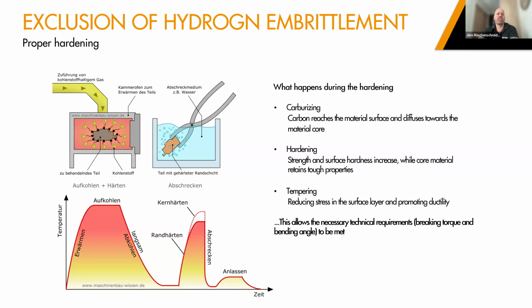So the hardening process in this case works in different stages. First of all we have the increased heat, then we have the carburizing phase, which you see, unfortunately, sorry, but the drawing I only had in German from our production installation guidelines. So aufkohlen means carburizing. That means we induce carbon gas into the material.